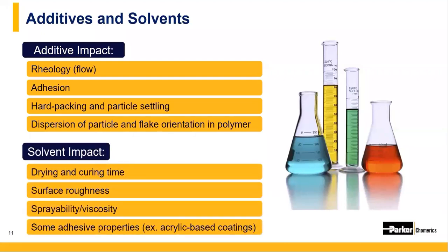So additives are put into a coating solution and are meant to impact the rheology, or the flow, of the materials. Additives are meant to work with the various particle fillers and are used to hold those metallic particles in suspension for greater periods of time and prevent particle settling. Hard packing occurs when the particles sink and create a dense layer that separates from the binder system and can make the application process very difficult. In general, additives are added in very small amounts, usually far less than 5% of the coating solution by weight. On the other hand, solvents are added in much greater quantities, usually anywhere from 30 to 70% by weight.